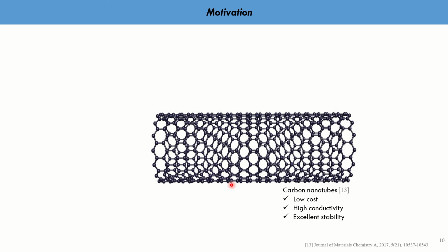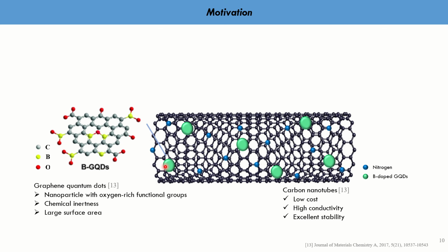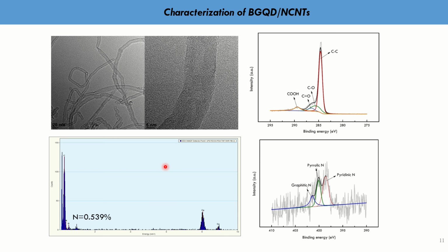Herein, carbon nanotubes were first chosen as a matrix owing to their low cost, high conductivity, and excellent stability, followed by pyrolysis treatment at 800 degrees Celsius for homogeneous nitrogen doping. Simultaneously, boron-doped graphene quantum dot, which could provide oxygen-rich functional groups as active sites, was synthesized via a hydrothermal process. Subsequently, boron-doped graphene quantum dots were adsorbed on the NCNT strongly by stirring and ultrasonication due to pi-pi stacking, further improving electrocatalytic ability. This is the morphology of NCNT by TEM.